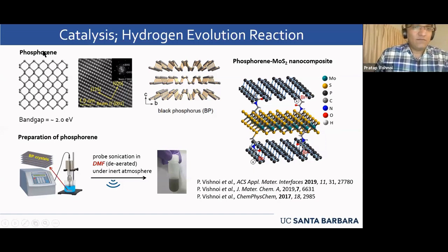We made a material called phosphorene, which I showed in the beginning. This is a single-layer material of phosphorus atoms. There is no other element in that. And of course, as I said, if you have one layer, you can put it under an electron microscope and see where atoms are. This is how it looks like. So you have a phosphorene sheet, and you put electron beam perpendicular and see the diffraction pattern and recreate the picture. You should see like that. The scale here is 1 nanometer. So basically, you can see atoms.